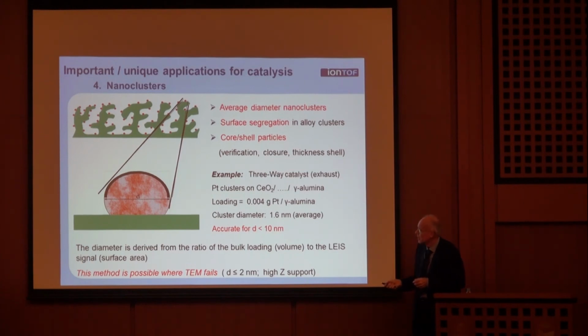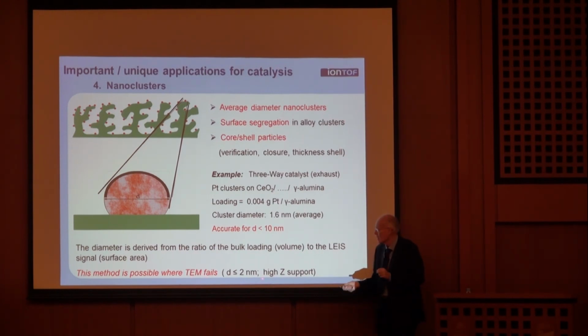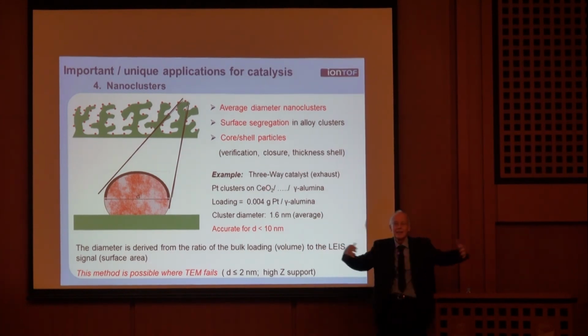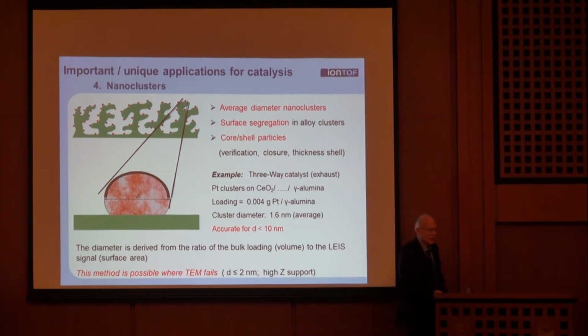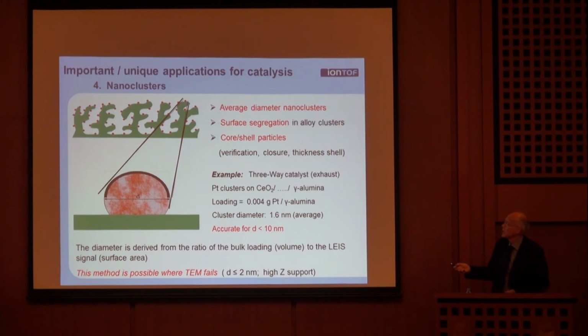So especially in cases where the clusters are small, it's difficult to do that with transmission electron microscopy, generally below 2 nanometer. It's really difficult. And also TEM is difficult if the support, like this one, has cerium and other things. It's very difficult to measure sizes of tiny platinum clusters. But by just measuring the signal, you can determine the average cluster size.